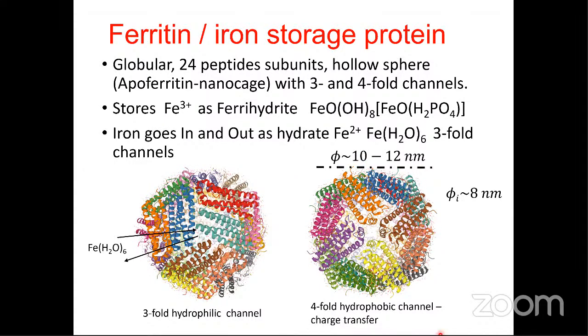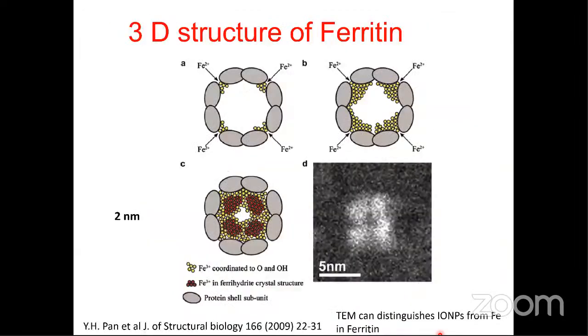So we need to ask ourselves if we can distinguish nanoparticles from this nanocage, and we can do it. High resolution TEM can see the ferritin structure that has a hole in the middle. You can see a hole here, a 2 nanometer hole. This makes it possible to distinguish between a complete nanoparticle and iron that went to ferritin and starts to become, so to say clearly, from bad iron to good iron.